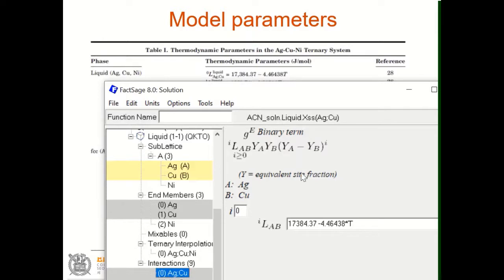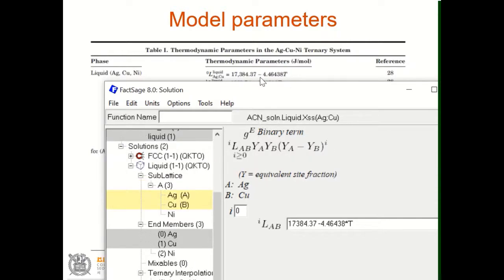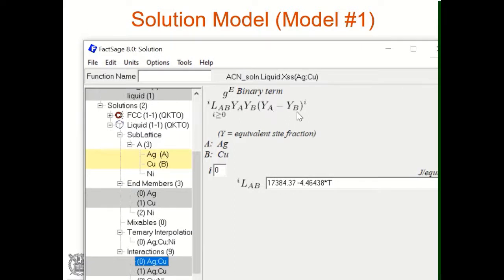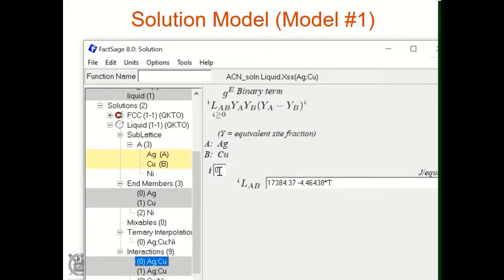L0 of Ag and Cu is this value. When you enter the Redlich-Kister type parameter, one thing to be careful about is the order of A and B: it is (X_A - X_B)^i. So L_ij is (Xi - Xj)^m, meaning i minus j order. In some papers the parameter is defined as X_B minus X_A to the power r, in which case you have to use the opposite sign. Always check the definition of their formula before assigning the parameter values.